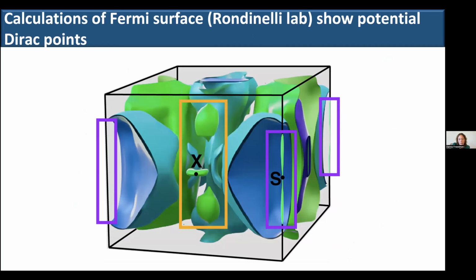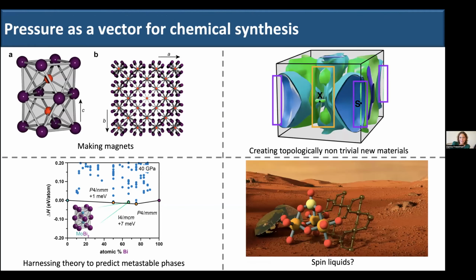shown a little bit better here, shows that the spin orbit coupling does create potential crossing points at the Fermi level, which could be the hallmark of a non-trivial topology, functionally meaning that the surface properties are different than the bulk properties. And that is promising. This is something that we're working on probing with ARPES, but we've had some pandemic-related difficulties. So we're very excited. And again, I'm sorry, these calculations are by the Rondinelli lab of the band structure.